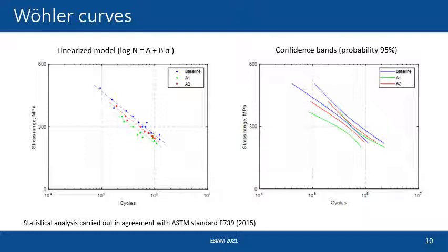We see that the effect of the A1 and A2 process parameters is only to move the curve towards the bottom. The three curves are almost parallel, with a fatigue strength reduction that is greater for the A1 set compared to A2. The three data sets are so near that the confidence bands are almost overlapping, in particular for baseline and for A2 that, as I said before, resulted in a fatigue behavior that is almost coincident.